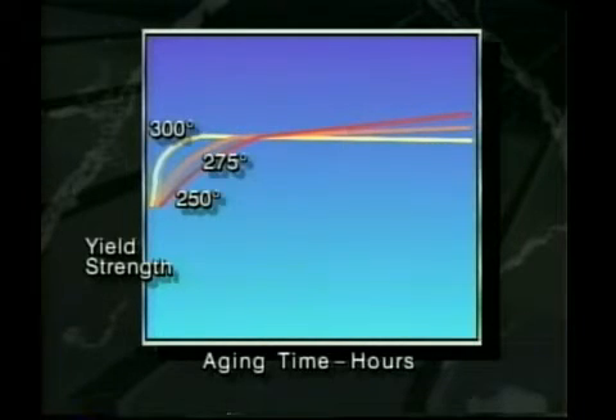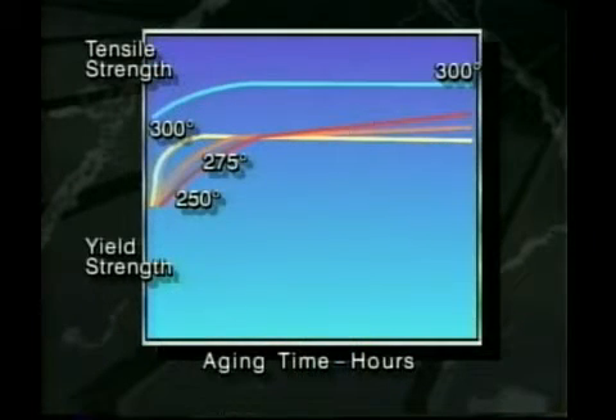At the highest temperature noted, 300 degrees, aging occurs very rapidly, and the maximum yield strength is achieved in about 8 hours. At lower temperatures, the aging reaction progresses more slowly, and it takes much longer to reach maximum strength. At 275 degrees, it takes from 36 to 48 hours for this alloy to reach its maximum yield strength. At 250 degrees, the yield strength has not reached its maximum value after 36 hours of furnace exposure. The maximum yield strengths which are reached for the different aging temperatures are shown in this table.